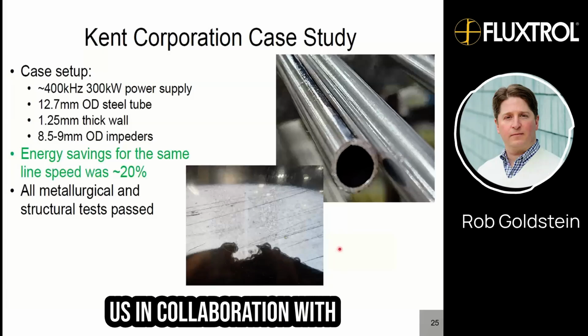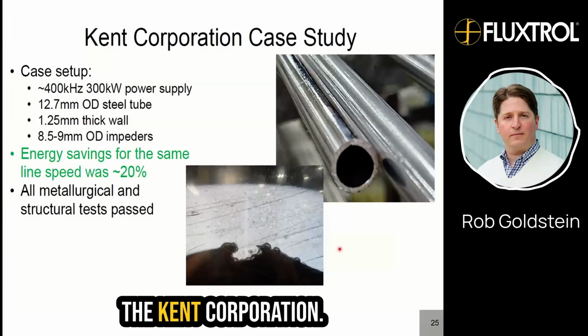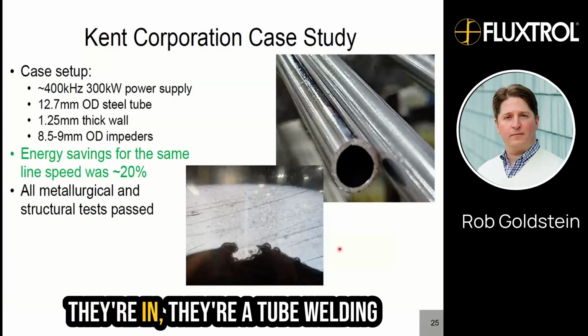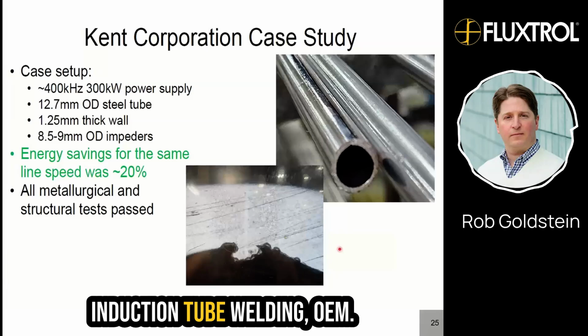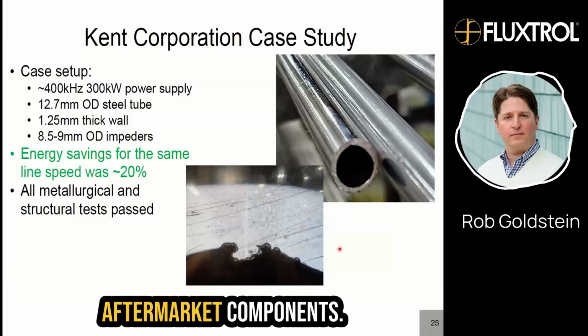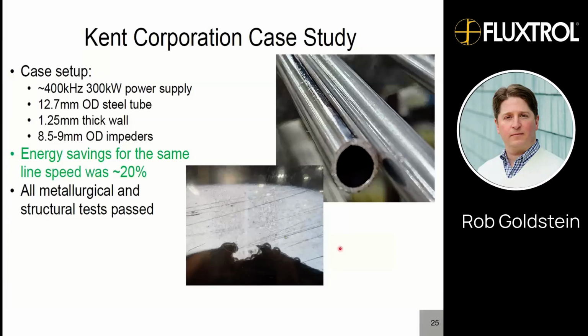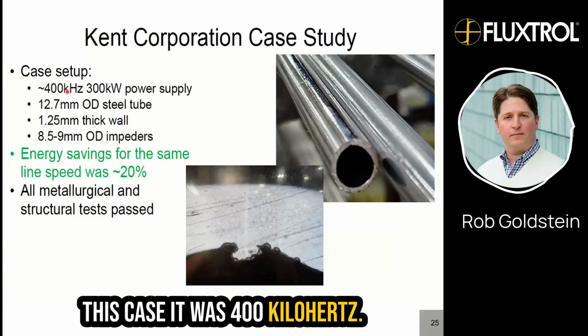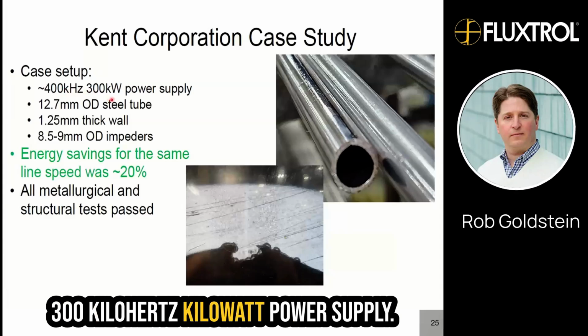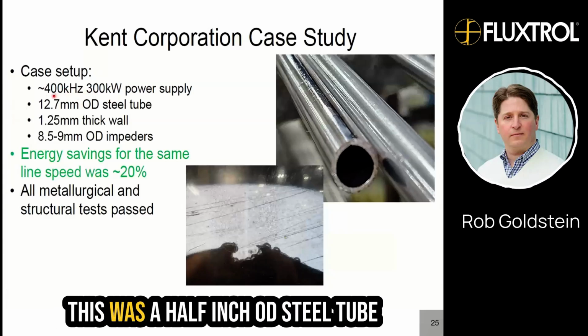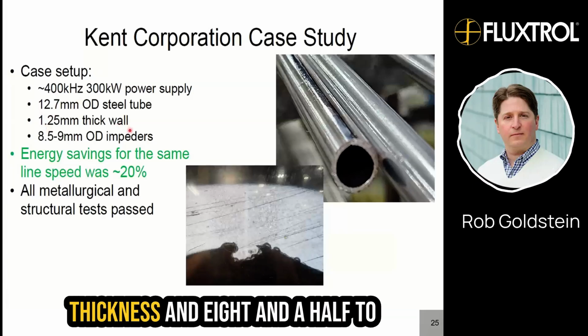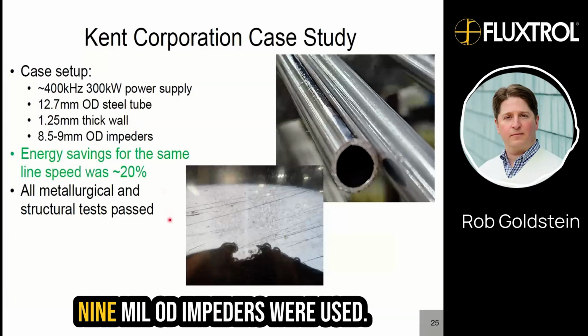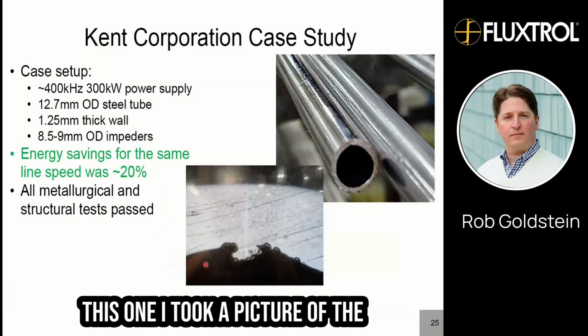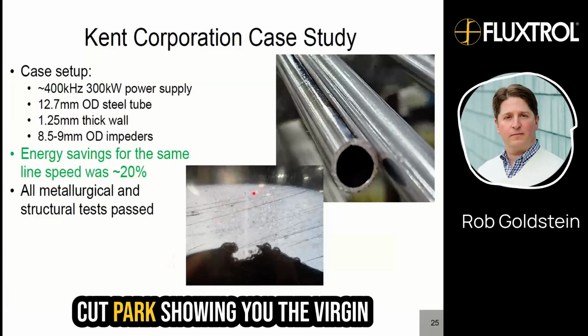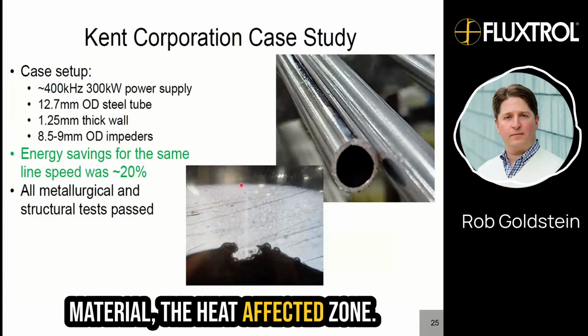This one was done in the US in collaboration with the Kent Corporation. They're a tube welding, induction tube welding OEM. So they sell systems, aftermarket components. In this case, it was a 400 kilohertz, 300 kilowatt power supply. This was a half-inch OD steel tube with 1.25 millimeter wall thickness, and 8.5 to 9 millimeter OD impeders were used.